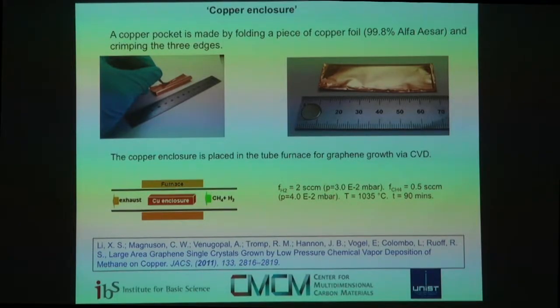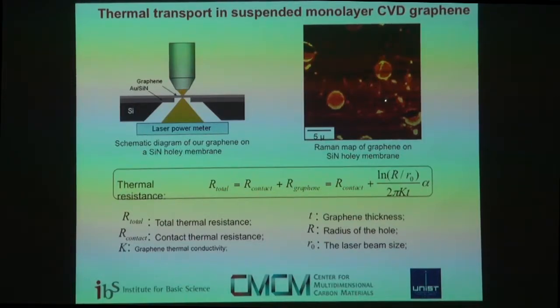And one thing I was very interested in probing was the thermal conductivity of isotopically labeled graphene. So the thermal conductivity of isotopically labeled diamond has been studied fairly extensively. Interestingly, there were no studies of the thermal conductivity of isotopically labeled graphite. I think there will be in the future. That's starting. So by having large single crystals, it then became possible to look at the thermal conductivity of CVD graphene and know that you were dealing with a single crystal that spanned many holes.